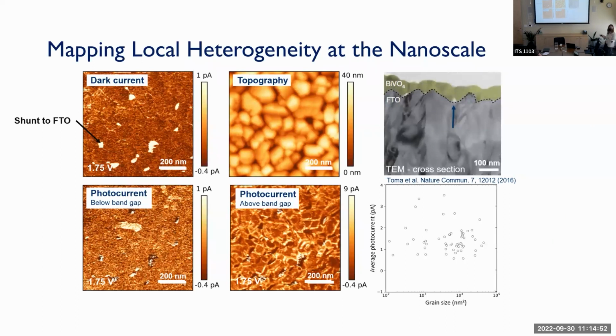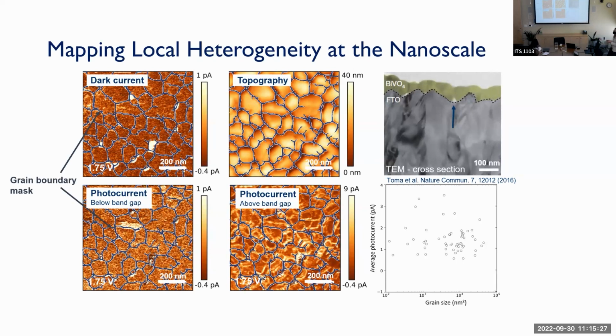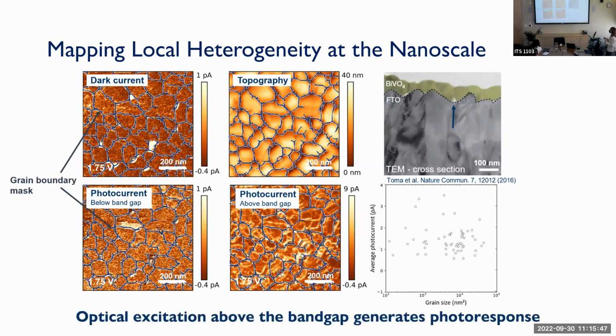However, and again, I'm not sure if anybody is working on atomic force microscopy, but if you do, you might know that it's a technique that is very prone to artifacts. And you can actually get very sidetracked when you look at your data if you're not careful. So something that we did here was trying to find if there were correlations between the topography data that we were measuring and the photocurrent that we were measuring. We didn't want any correlation, because in that way we knew that there were no artifacts. So once we did that, we started with the statistical analysis. And with statistical analysis, you have the topography here, you have the maps of the photocurrent, and you have the control, which is basically when you're not shining light.